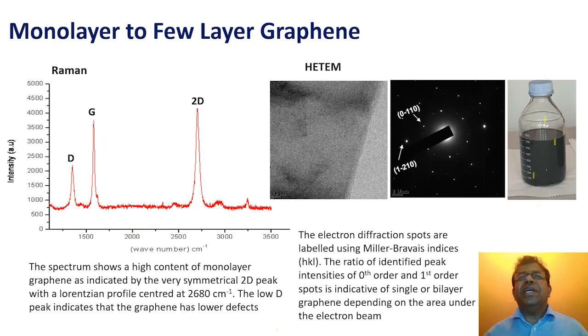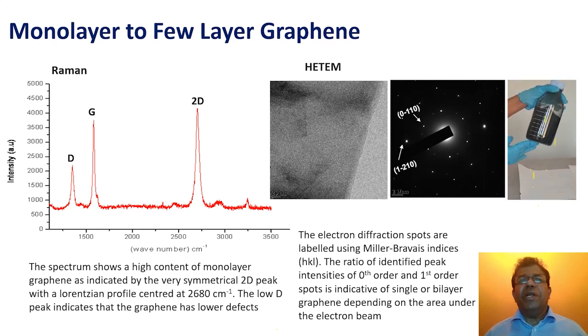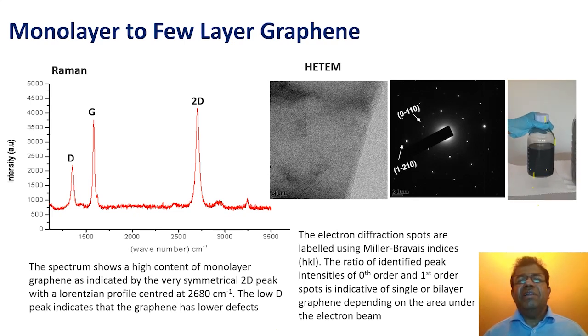Raman spectroscopy is a useful technique for characterizing sp2 and sp3 hybridized carbon atoms, including graphite and graphene and other carbon isotopes. The 2D band is a second-order two-phonon process and exhibits a frequency dependence on the excitation laser energy. The 2D band can be used to determine the number of layers of graphene. The 2D band of a single layer is much more intense and sharper compared to the 2D band of multi-layer graphene. In the samples which have been produced, the spectrum shows a high content of monolayer graphene, as indicated by the symmetrical 2D peak with a Lorentzian profile centered at 2680. The low D peak suggests that the graphene has low defects.